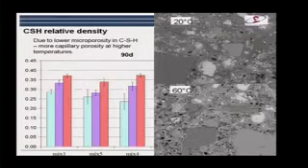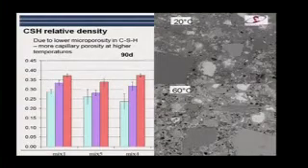And then when we go to investigate this further, we can actually see that the temperature has had a quite dramatic effect on the calcium silicate hydrate phase. So this one was cured at 20, this one was cured at 60. You can see here that the CSH here is much darker than the CSH here. And the fact it's much darker indicates it's less dense. So the brighter color indicates a higher density. And you can measure this systematically. What's the gray level? This is what's shown here. So you see 20, 40, 60. The gray level, proportional to the density of the CSH, increases.